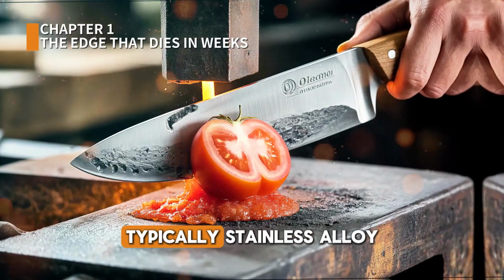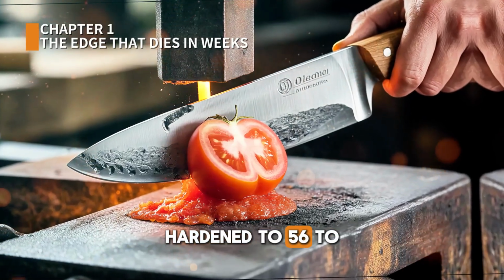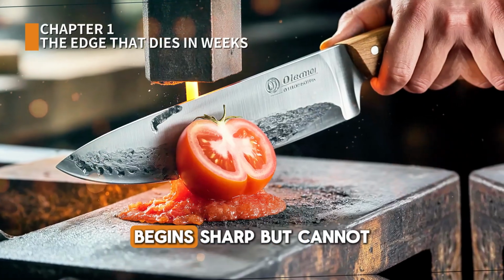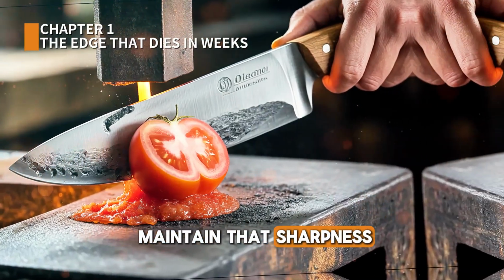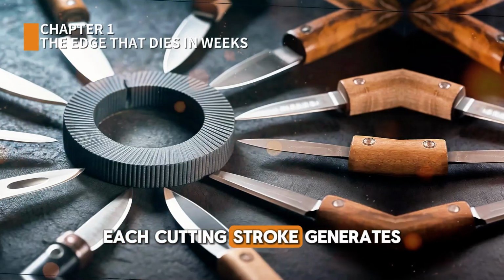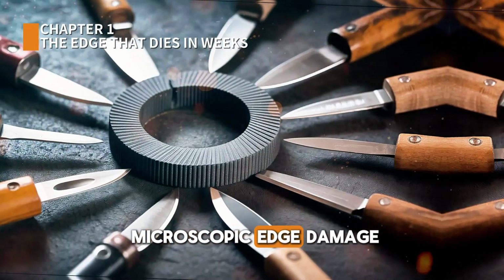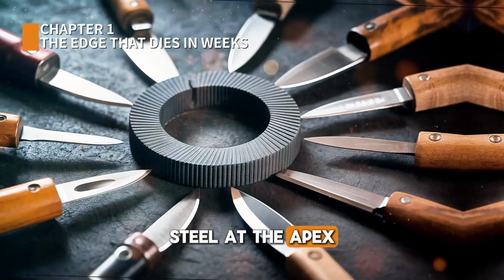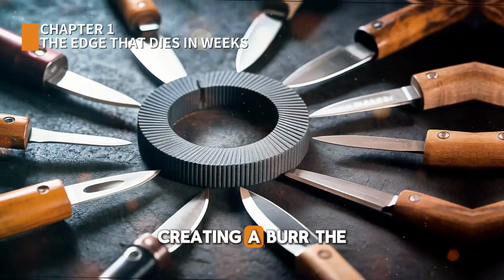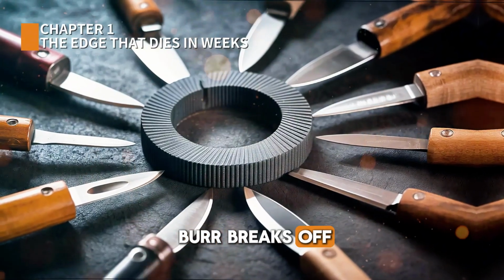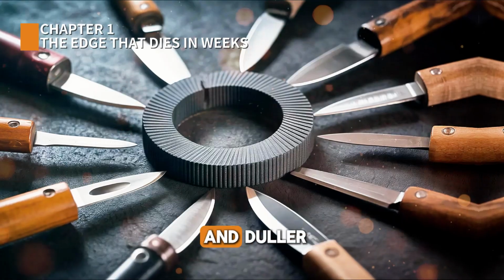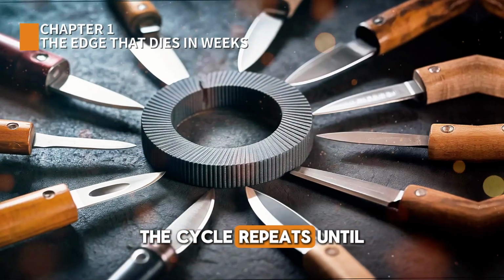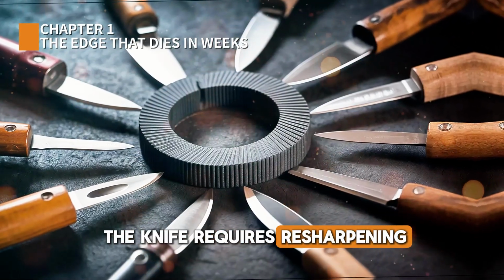The steel, typically a stainless alloy hardened to 56 to 58 HRC, begins sharp but cannot maintain that sharpness. Each cutting stroke generates microscopic edge damage. Steel at the apex folds over, creating a burr. The burr breaks off, leaving the edge thicker and duller. The cycle repeats until the knife requires resharpening.